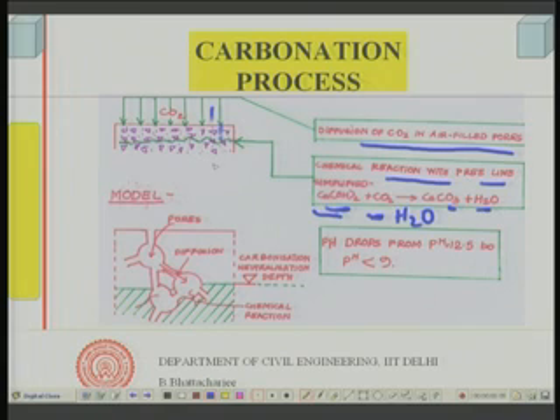And this causes a reduction in the pH of the concrete, because when it consumes all the calcium hydroxide, or all the alkaline material present in the concrete, the pH of the concrete will come down. This process lowers the pH, and when the pH becomes below 9, the passive film can get depassivated. The pH of the pores was initially around 12.5 in concrete, or even higher, 12.7, 12.8, very close to 13, and then it comes down. Carbonation occurs through the pores.